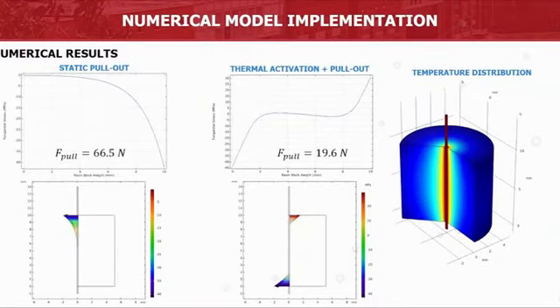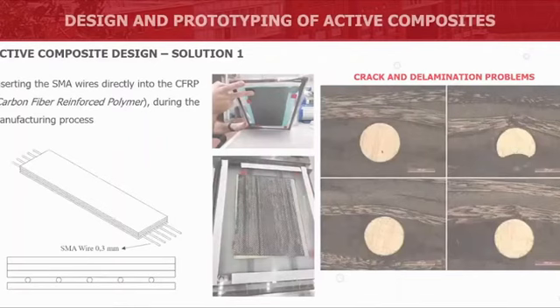Some results are shown in this slide, particularly for the type 1 experimental test and the type 3 experimental test. And the interesting thing is that both tests show the same distribution of the shear stress along the interface between the SMA wire and the resin block.